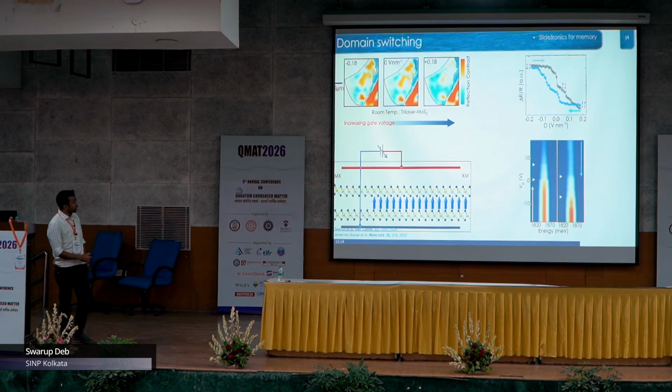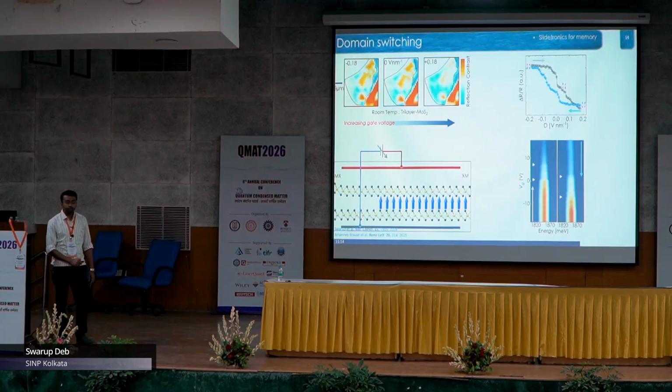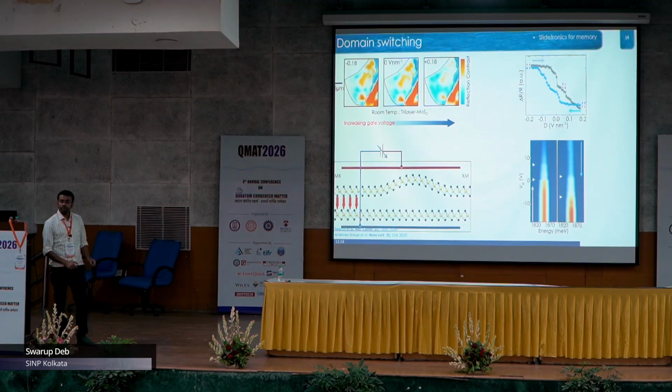And we have more proof for that. If I now put my white light spot close to the boundary and do this experiment, the reflectivity as a function of external voltage, we see that they trace out this very nice hysteresis loop, very similar to the MH loop or the PE loop of a ferroelectric material. And what is interesting is that this switching is very, very fast.